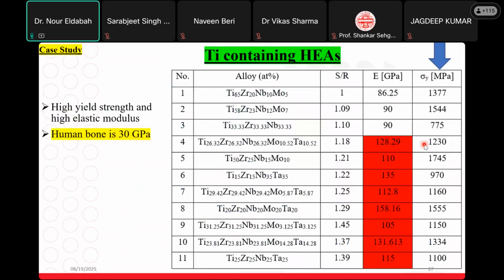But if you look at this table here, we will face the most important problem, which is the elastic modulus. We spoke about elastic modulus as the most important characteristic. If you didn't consider the mismatch, you will deform the human bone. Actually, we will have a very high yield strength, and this is very useful for us because high yield strength means that we will reduce the implant size. But the elastic modulus has a severe value exceeding 100 gigapascals, so we will face a problem of mismatch, knowing human bone is around 30 gigapascal. So